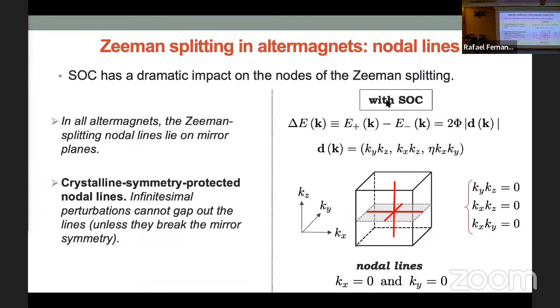Now, here's the interesting property. Now that I'm allowing the spin to see the lattice, you see that all these lines are always residing on the mirror plane of the lattice. So it turns out that these lines are actually crystalline symmetry protected nodal lines. They're protected by this mirror symmetry. And this is one example, but we saw that in every case that we looked.